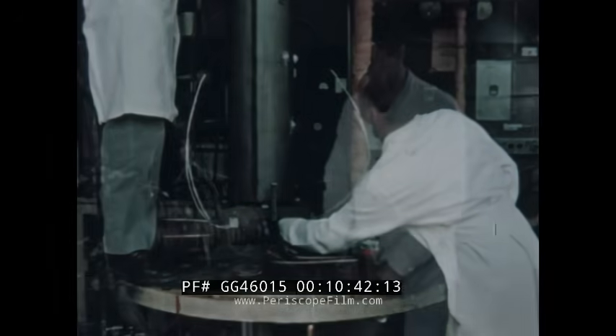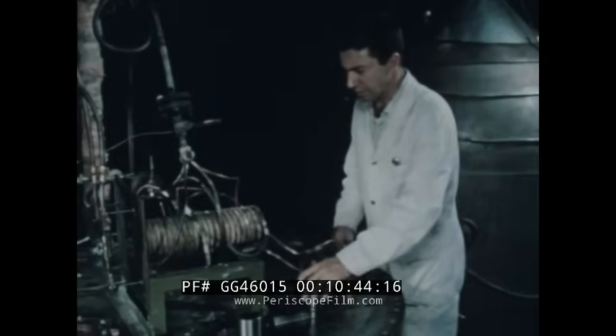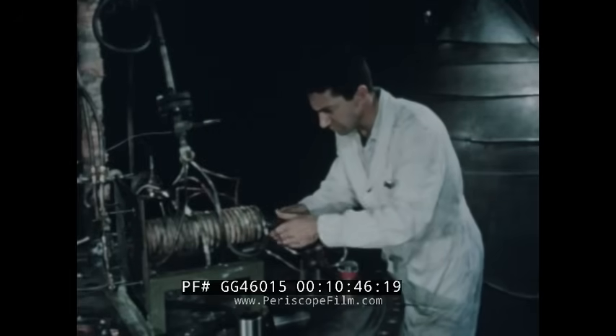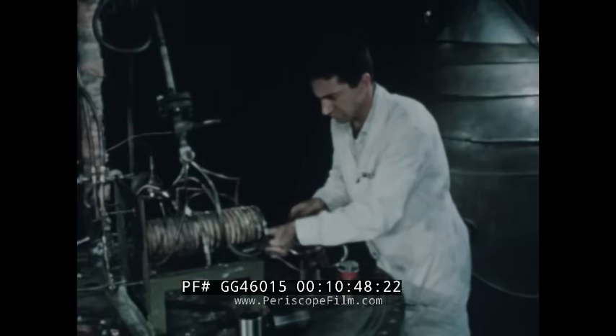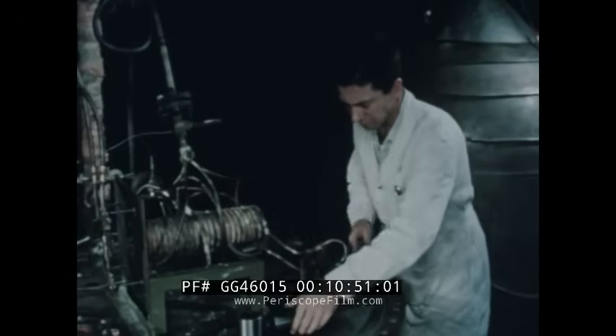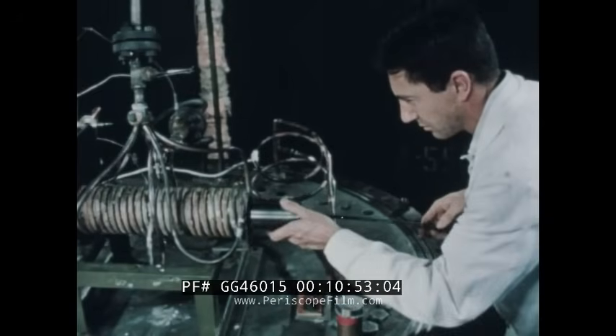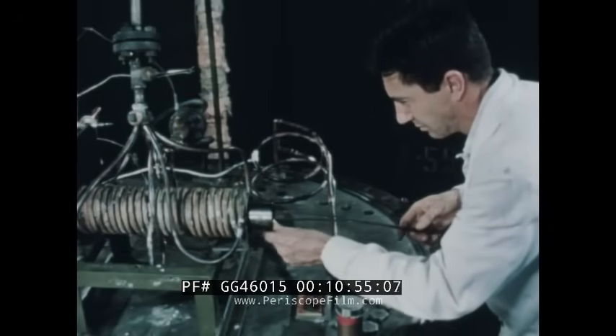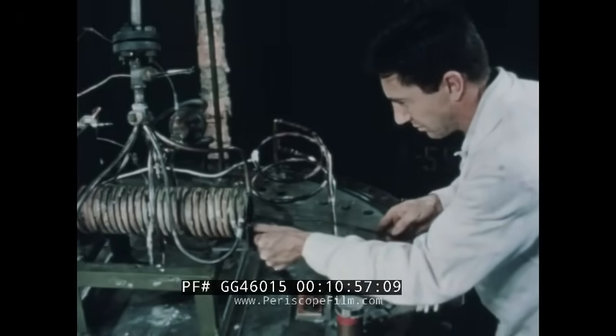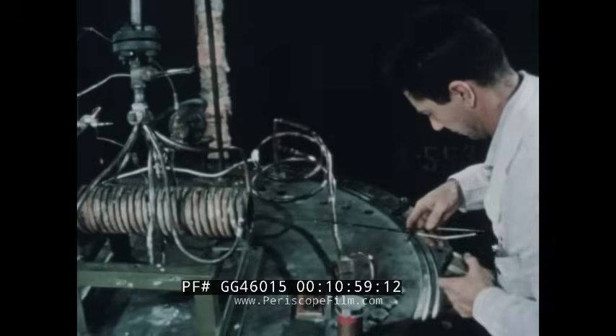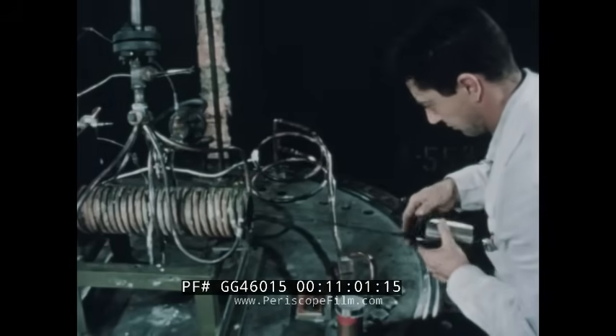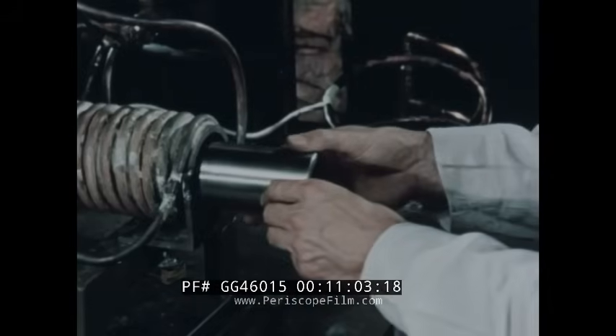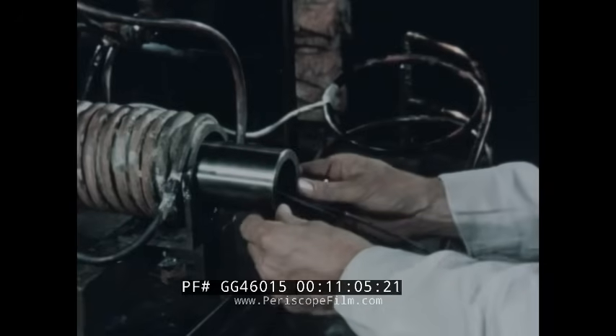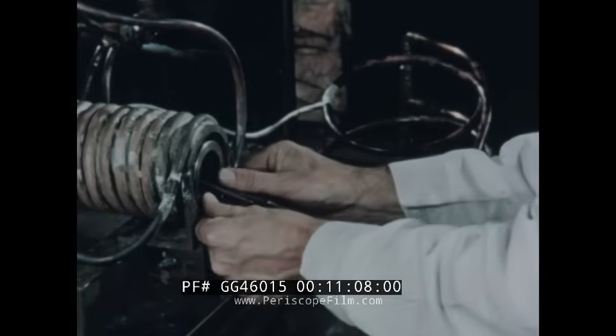These rings were thermal cycled in another series of tests to investigate physical changes which might occur under operating temperatures. They were cycled 500 times for a maximum of 1,500 degrees Fahrenheit down to 700 degrees, with a gradient across the rings of 300 to 400 degrees. These tests indicated that the changes in size would be well within acceptance limits.